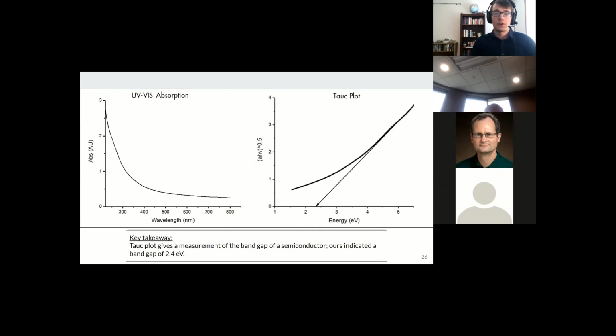Optical absorption of the powder was performed by placing a small amount of carbon-removed powder in an isopropyl alcohol solution. The carbon had to be removed first so that the amorphous carbon coating would not interfere with the absorption signal, and an approximate band gap value could be determined through what is commonly referred to as the Tauc plot.